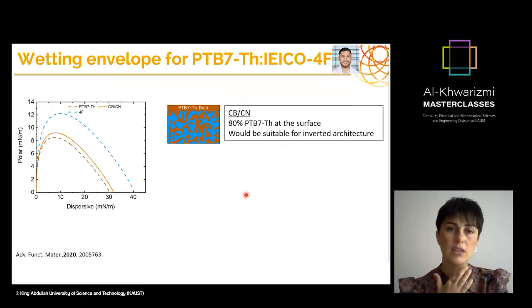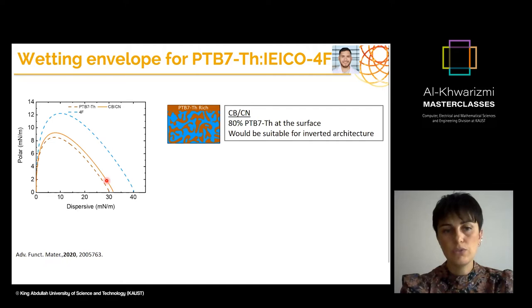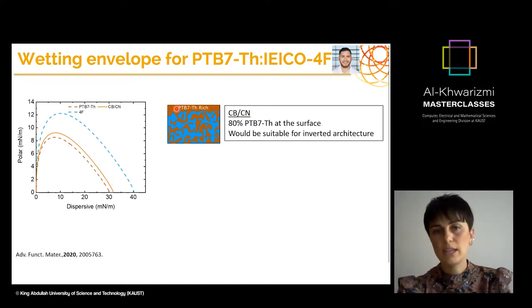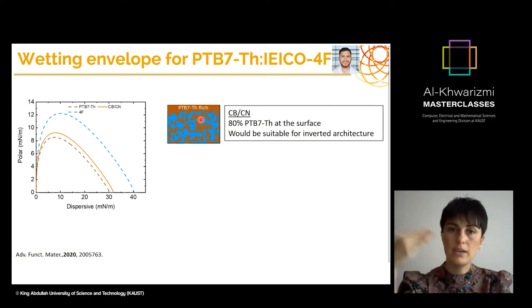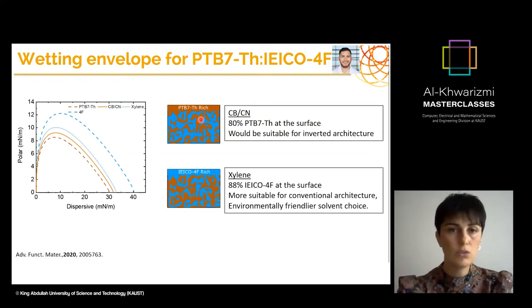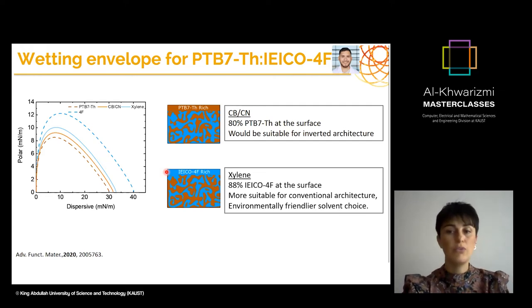So we created this wetting envelope for PTB7-Th, as you see here, for the donor and the acceptor. And using different solvents, as in the first case, chlorobenzene and chloronaphthalene, we found out that most of the donor material sits on the top if we coat it with this type of solvents. And if we move to a more environmentally friendly solvent, then the acceptor molecule starts to be on top, which is actually more suitable for conventional architecture with this type of environmentally friendlier solvents.